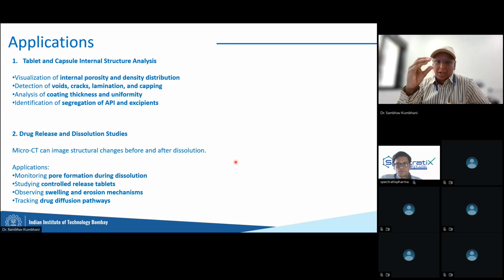Sometimes when we pack the formulation into a tablet, there can be cracks and voids formed. You don't like a tablet with a crack in it, right? So you want to make sure that cracks and voids are not formed, and that the porosity is the way it should be, things like that.